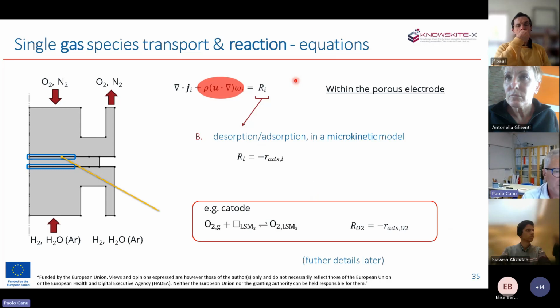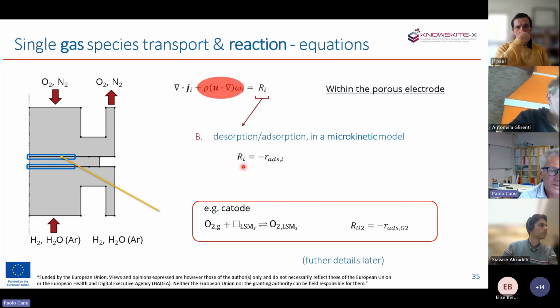On the other hand, the approach to the consumption of gas species within the electrodes means that the rate of production is the opposite of the rate of adsorption. So on the cathode side, that means that oxygen as a molecule in the gas phase can interact with the surface site. In this case, I took an equation mentioning LSM instead of LSCF, but the concept is the same. That's a surface site, typically on the electrical conductor part of the composite, resulting in adsorbed oxygen on the surface. And that's a process of removing oxygen from the gas phase, bringing it to the surface. But I'll give you some more detail later about this implementation.